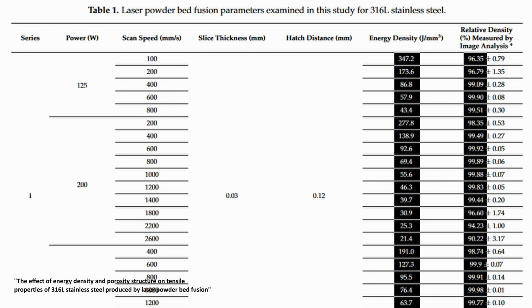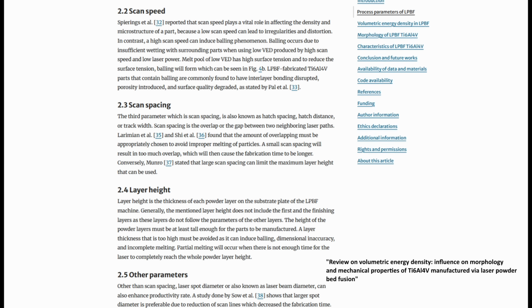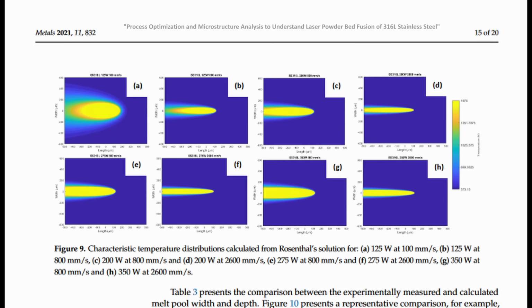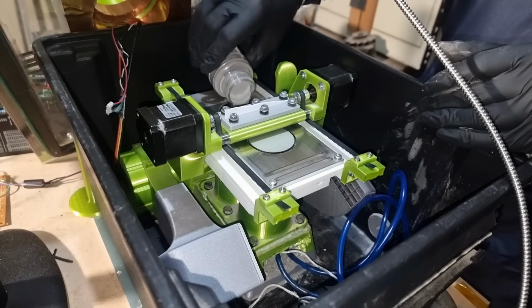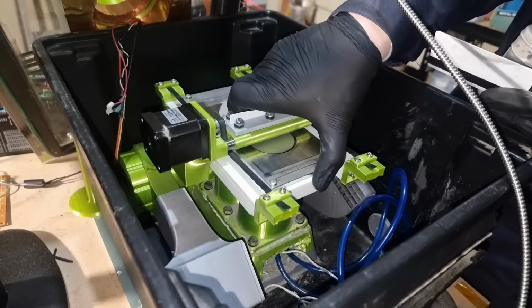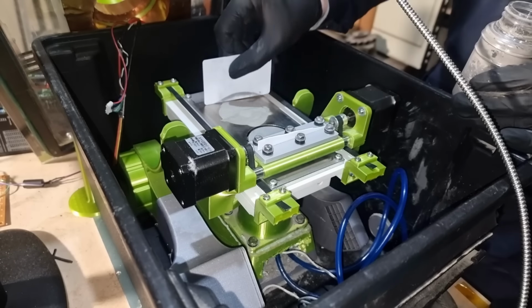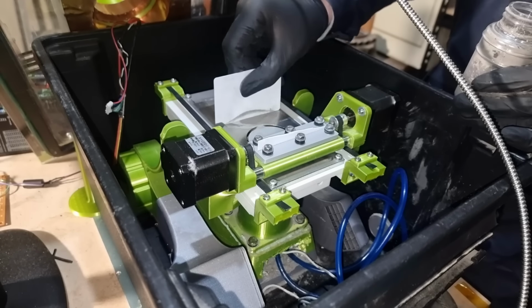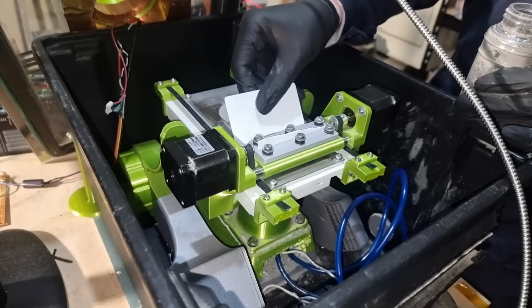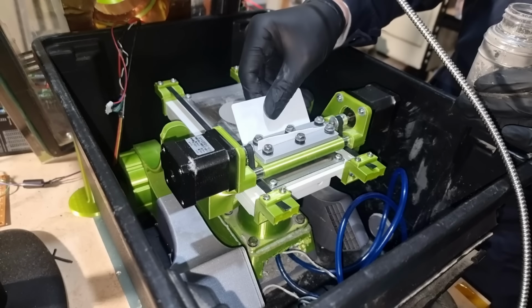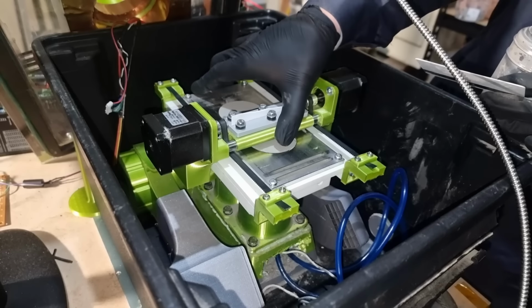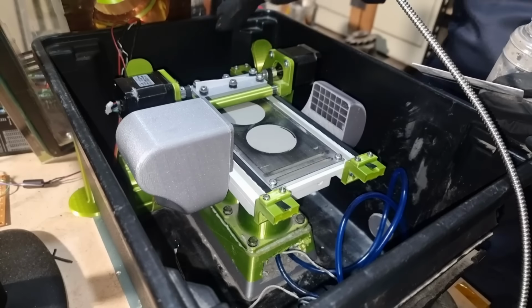The problem is these numbers can vary wildly depending on the system itself, as the applied energy is not the same as the amount absorbed, and that can be influenced by factors such as spot size and the behaviour of the melt pool. For 316 stainless steel, the numbers are commonly in the band of 50 to 80 joules per millimetre cubed, but this is assuming that the processing conditions are on par with that of a commercial machine. As I can't concentrate my laser as well, things would stray towards the experimental, and with that we continue forward.